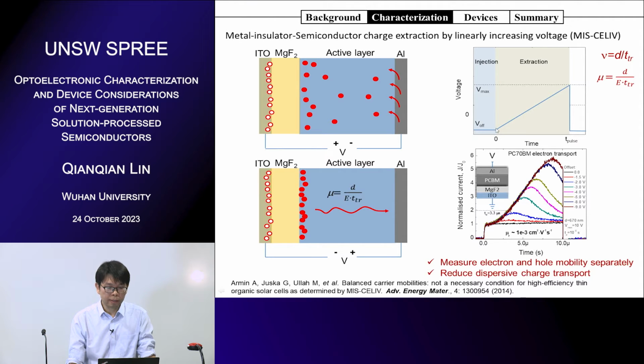Then we start to extract the carriers with reverse bias. So we immediately change the sign of bias, and we linearly increase the bias voltage. We can also get the transient, and in this way we reduce the dispersion of photo generation. So we want to improve the method to get more or less dispersive transient from this CELIV. And this method can also tune the work function of metal electrodes.